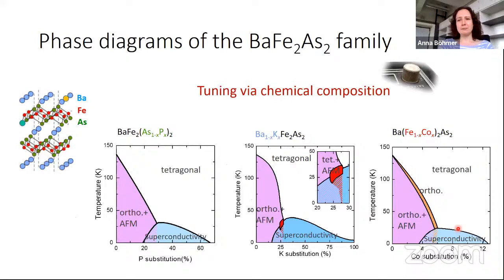So let's go back and summarize a bit. And I like summaries in terms of phase diagrams. We've seen this one phase diagram with a structural distorted antiferromagnetic stripe-type phase and superconductivity. We've seen this intermediate phase where my distortion suddenly disappeared, this little pocket. And we've seen this strip of a strange nematic phase that is sort of in between these two.